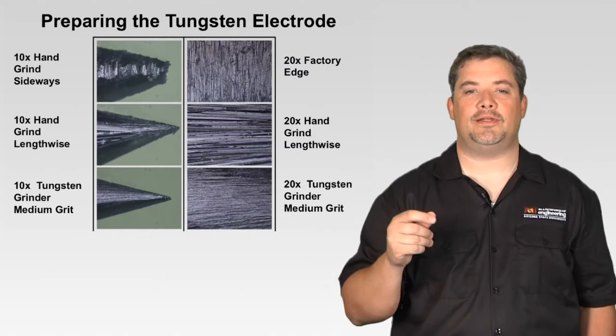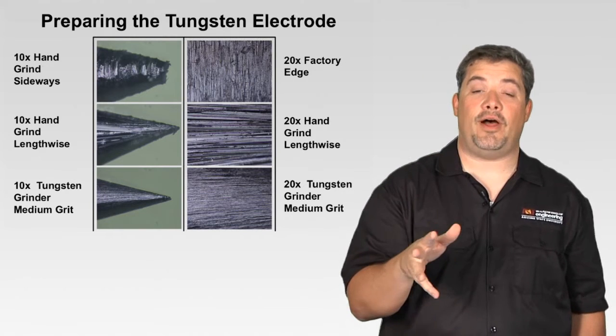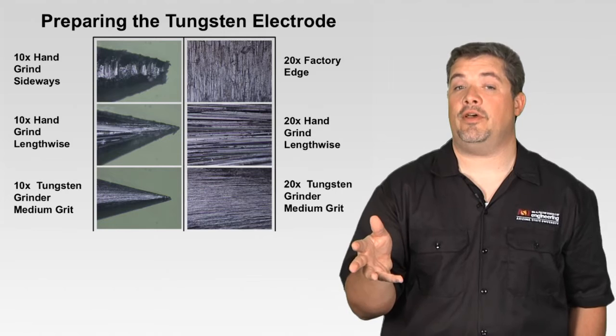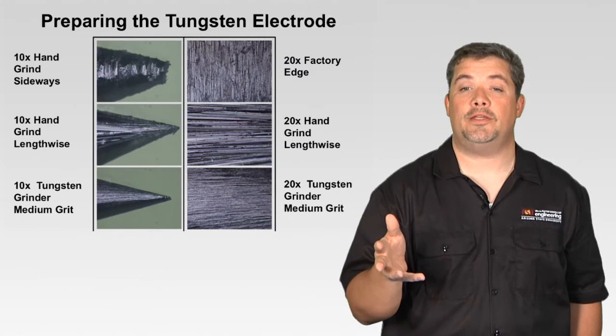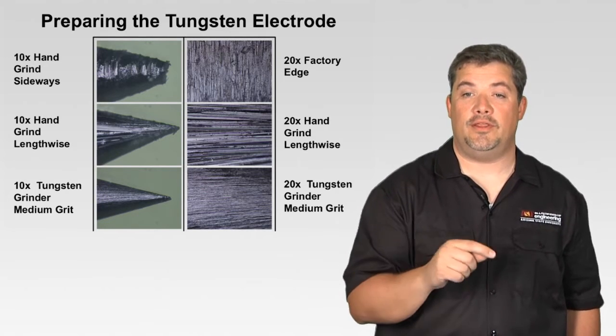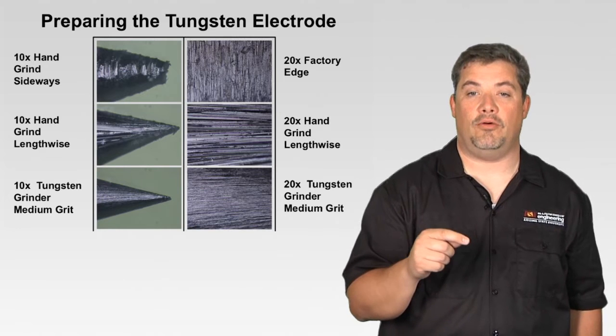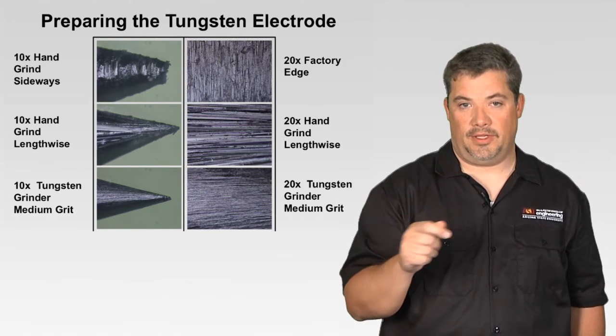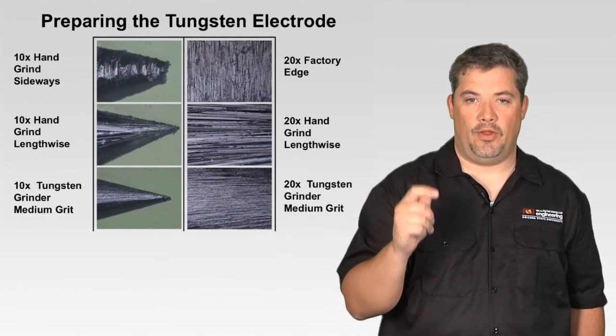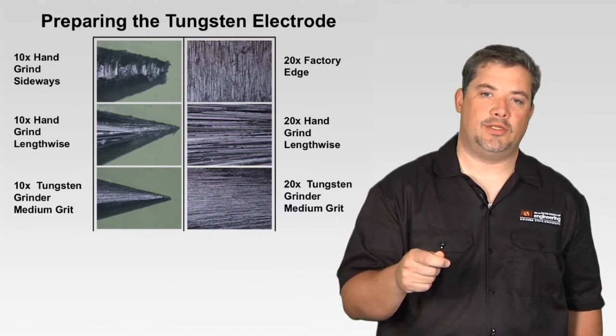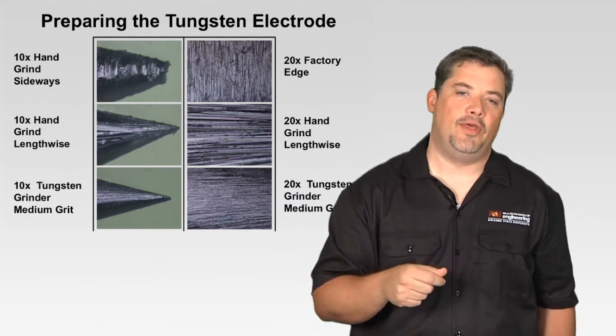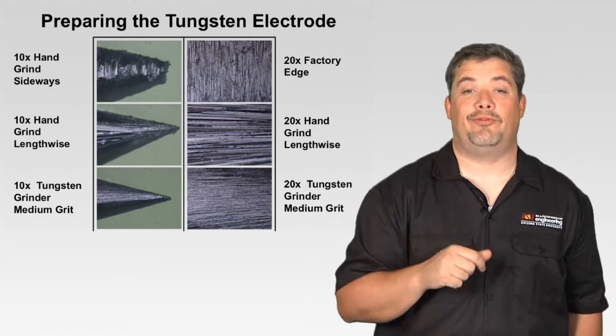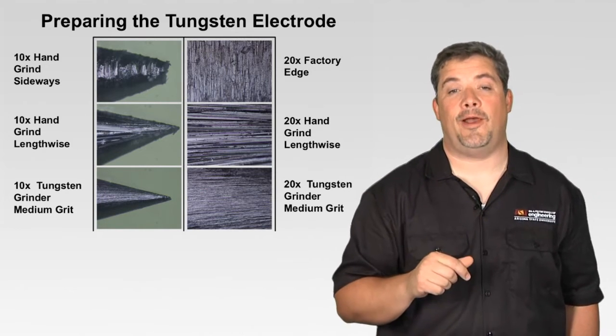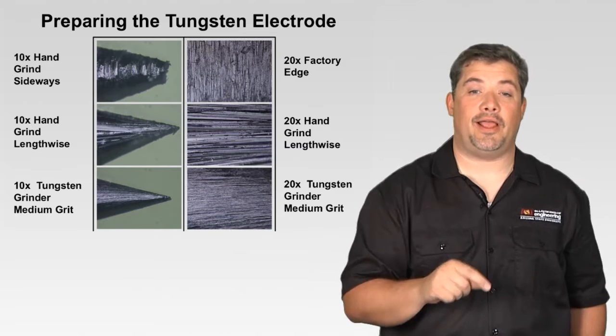So those are little pieces of tungsten that could potentially fall off and get into the weld and potentially cause a failure in some critical applications. On that right image, you can see the 20x hand grind lengthwise, how deep those grooves are. Certainly it's in the right direction now, but they're so much deeper and there's burrs involved, may be a bad thing. For what we're doing in the lab, we'll be just fine. For your general welding, probably just fine. But critical applications, you need it like on the bottom.